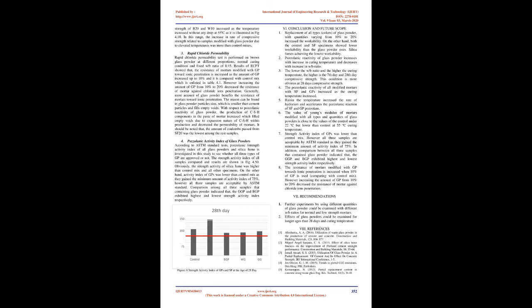This process is valid for SF20, B10, G10, G20, and W20. But the compressive strength of B20 and W10 increased as the temperature increased without any drop at 55 degrees C, as it is illustrated in Fig 4.10. In this range, the increase in rate of compressive strength related to samples modified with glass powder due to elevated temperatures was more than control mixes.